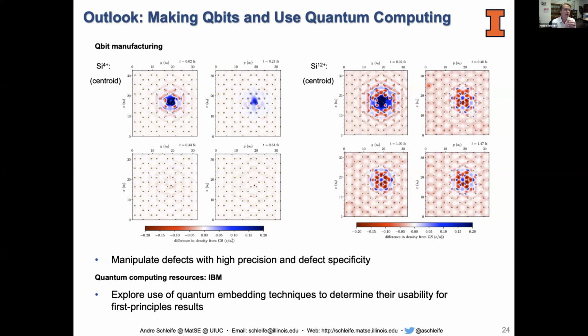So the first one, and I want to start with that because I think that's the one where we're maybe closest to coming up with a solution, not a solution maybe, but with interesting data comparable to experiment, is we want to use this excited electronic state and exploit it to tweak defects in the material, potentially for qubits, but again, that doesn't matter so much for our case. The qubit analogy comes simply from the fact that the way you make NV centers in diamond, one of the ways is to ion bombard the material. And I think that this excited electronic contribution to diffusion can be exploited for that.